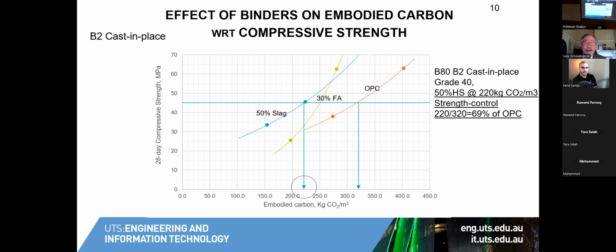So to select the concrete which satisfies both the diffusion requirement and strength requirement, at the end, in this example, we would have chosen a 50% slag blended cement concrete, which produced an embodied carbon of around 220. Now, if you compare this to an OPC concrete, for instance, you'll find that we basically save about 30% of the embodied carbon. And that's the potential that innovative use of SCM enables us to choose a concrete with the lowest embodied carbon possible, which meets all the requirements.